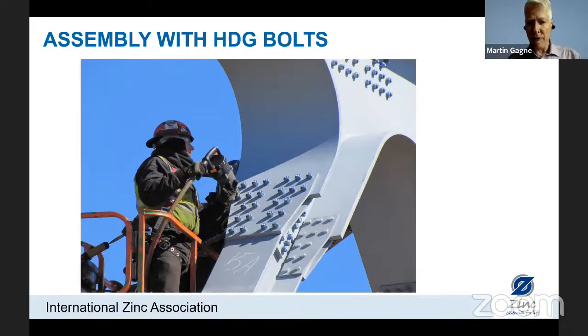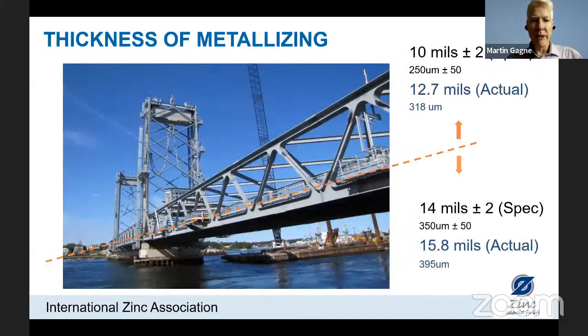We can see the overlap of these connections here. We will have zinc in that gap. And again, this is very important. It will eliminate or greatly reduce any potential for crevice corrosion, which can usually start in these locations. Now, an overview of the bridge again. The specification called for a thicker coating at the bottom of the bridge, which is closer to the salt water, and a thinner coating above the bridge deck, which would be in a less corrosive environment.